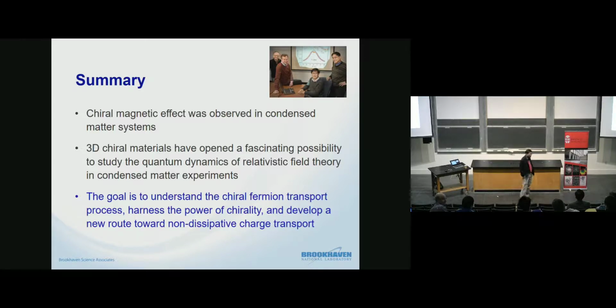No, for these ones, this is a very good question, right? For very thin films, it's not 3D, because it becomes a topological insulator there, and then you lose chirality, it's not good. But if you get to, for instance, 100 nanometers over there, it still follows the 3D behaviors. But if you look at the monolayer or something, then there's no chirality there. So the film doesn't work for this particular case.